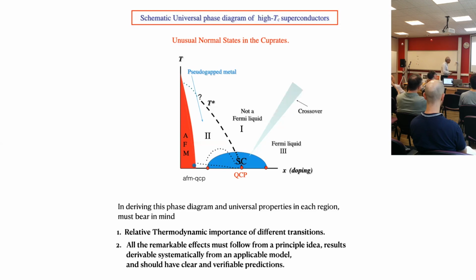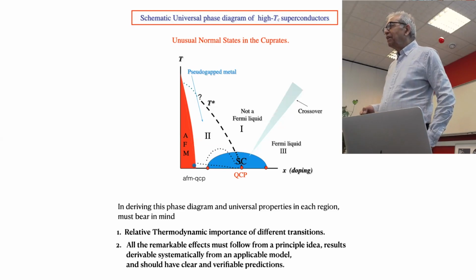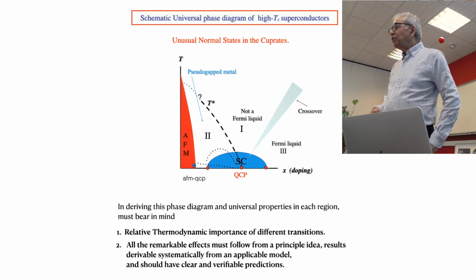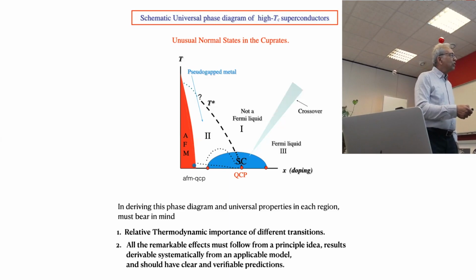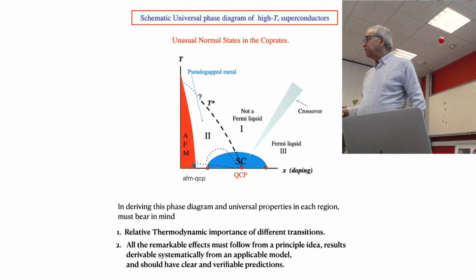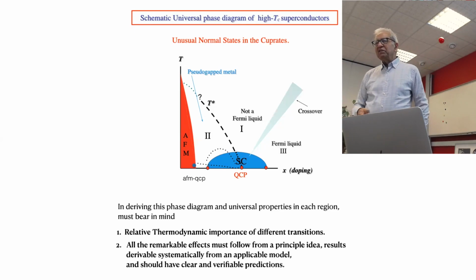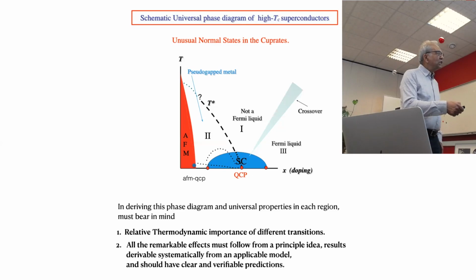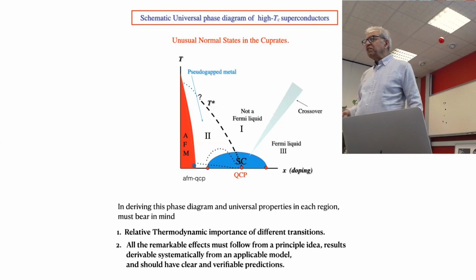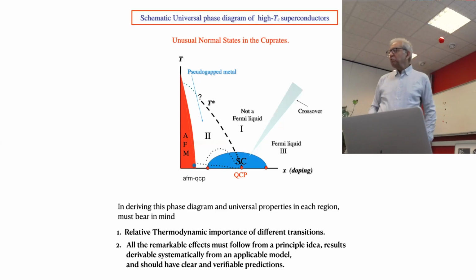In writing down this phase diagram, one should bear in mind that there is an experimental way to measure the energetics of the important changes by thermodynamic measurements of specific heat or magnetic susceptibility. And from that point of view, there is the half-filled antiferromagnetic region, which I will not speak about, but which should also be given by the same model with which we treat the rest. There is superconductivity. Then there is something that we did not know in the early days of HTC, but we know now. There's another line where every property changes.